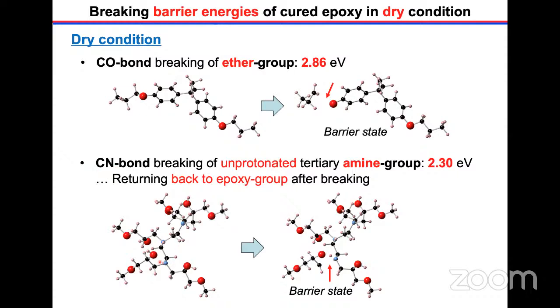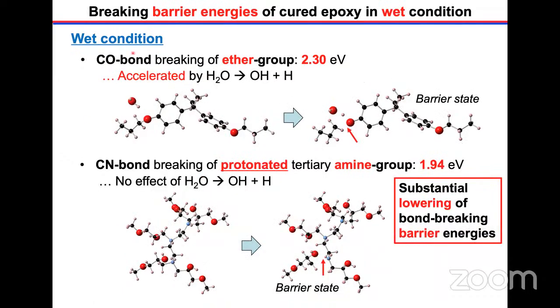And in the case of the CN bond of the amine group here, in this case the amine is not protonated. This is a dry condition. In this case, the amine group is 2.30 electron volt. Then after the reaction, coming back to the epoxy group after the breaking. Then if we have the wet condition, in this case, CO bond breaking is assisted by the breaking of H2O, something like this. The barrier energy becomes 2.30.